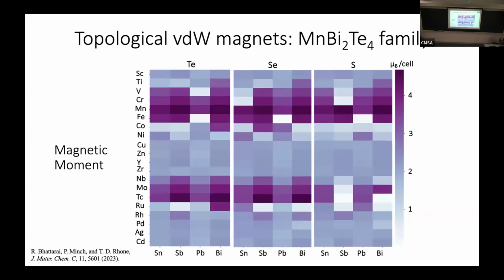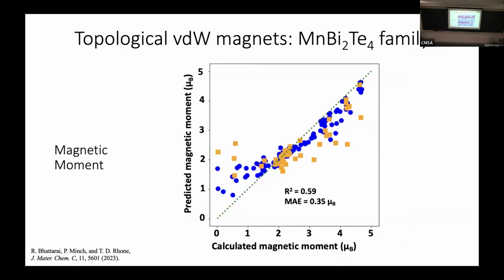These are some of the results from DFT. This is the magnetic moment. Magnetic moment is like the magnetization of the material. Again, there's a pattern in the data, and we'd like the model to learn the pattern for quantitative predictions. We did that with a simple machine learning model. I think we used an XGBoost classifier or XGBoost regressor. I forget exactly what it was, but not a neural network. And we can plot the calculated magnetic moment on the horizontal axis and the predictions on the vertical axis. Again, this dashed line is a guide to the eye. And for material search purposes, the model is working pretty well.